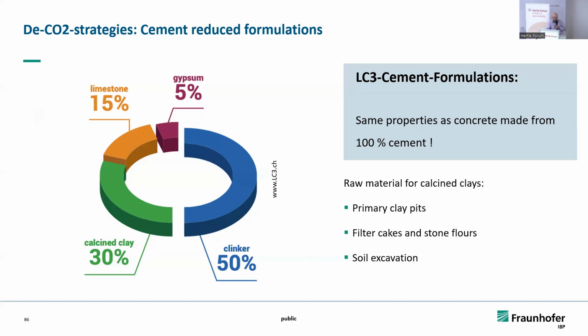And when the steel industry will change to hydrogen technology, we'll also have a lack of about 8 million tons of blast furnace slag. And if the cement industry wants to reduce the clinker content down to 50%, we need about, in Germany, about 16 million tons of supplementary cementitious materials in about 6 years from now. So it's a big challenge.